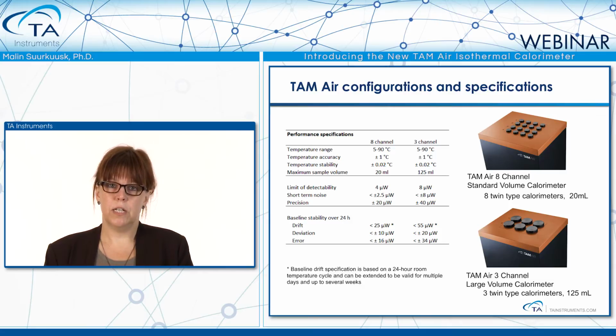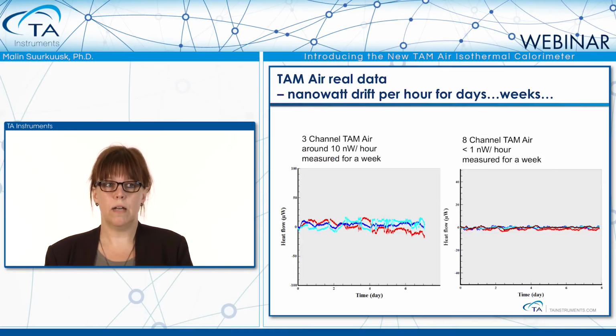This specification doesn't mean that the temperature is constantly drifting every 24 hours. It's more that it's based on the 24-hour cycle of a room temperature variation. And the baseline stability is actually much better than you see on this specification, because if you elongate the time, you will see that the baseline stability is essentially 0, which can be seen in the next example with real TAM Air data that's been measured for several days. We can see that the drift is nanowatt per hour, measured for several days or up to a week. So we have nanowatt drift per hour or day, even if you can see some fluctuations within a 24-hour cycle.